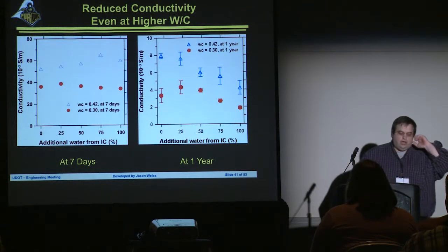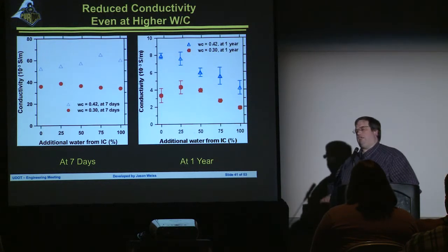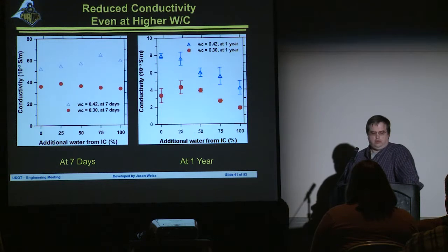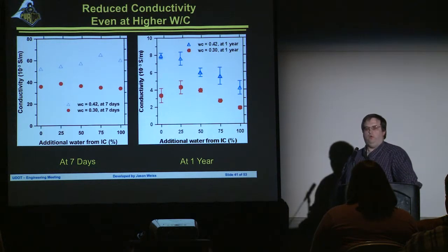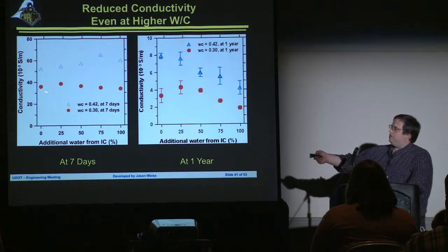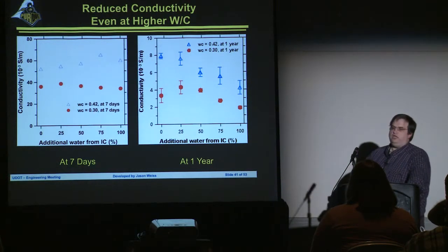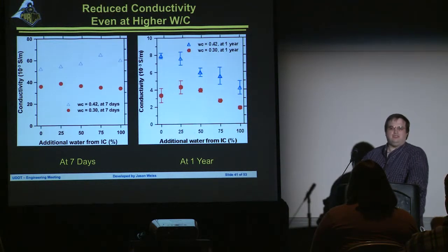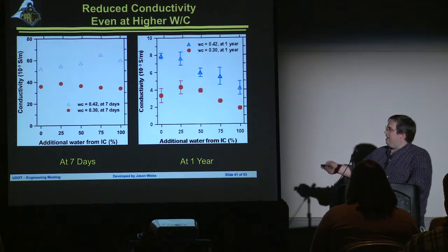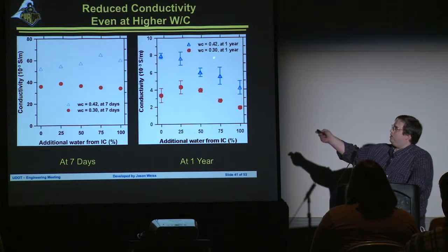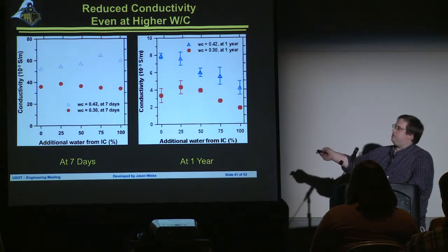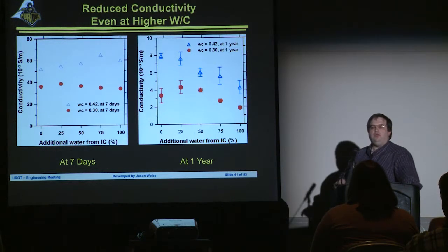Now, a lot of people are going to say, well, this only works if I get to a 0.2 water to cement ratio concrete, and we don't do that. We pour at a 0.36 or a 0.4. What I'm going to point out here is maybe early on, 1 day, 3 days, 7 days, you're not going to see a huge benefit because the system still has a lot of water to continue hydration. After a year, though, we can look here at the red dots, which are a 0.3 system, and a 0.42 system, which are these blue triangles, and we see that this helps both systems.